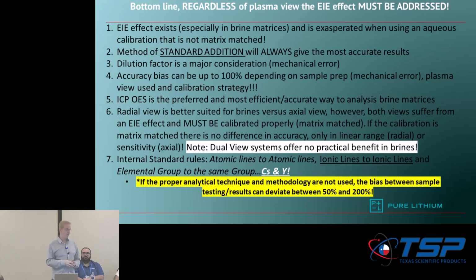There's ways around it. When we run dimethyl carbonate, we use isopropyl alcohol, straight isopropyl alcohol, or 90% I should say, isopropyl alcohol, and we adjust it so that the carbon bands are similar, and then we add an internal standard and we get the transport effects that way. Dilution factor. The less you can dilute, the better. Especially when you're working with something like lithium, I cannot tell you how important it is to have a good balance.